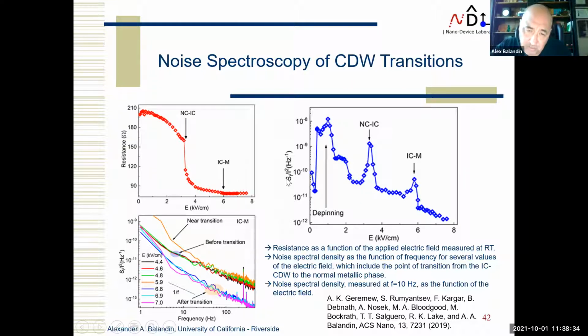If you look at this picture of spectral density, as a function of the same applied electrical field, this is your nearly commensurate to incommensurate transition, which has a strong peak. And then we also have a strong peak again at the incommensurate to metallic transition. And we thought, okay, our noise spectroscopy is a good tool to check properties of materials and phase transitions.